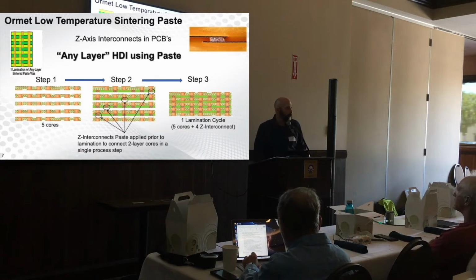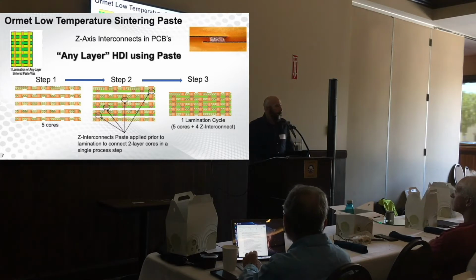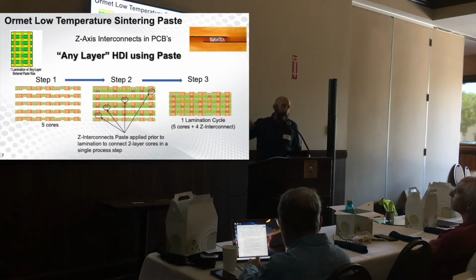Yes? And will this maintain the same dielectric constant of the copper plate when you do the bond? I think you're asking the conductivity difference, right? Between raw copper. IR drop. Right, so it is not as conductive as copper metal, bulk copper metal. However, unlike a via that may not be completely plated shut with copper, the whole via structure is the metal. So you don't see that discontinuity between layers. And usually the length is very short, so it's not a problem in the design. So essentially you can stack as many two-layer vias through the substrate.